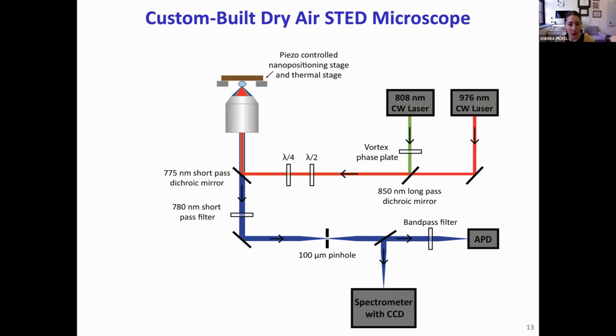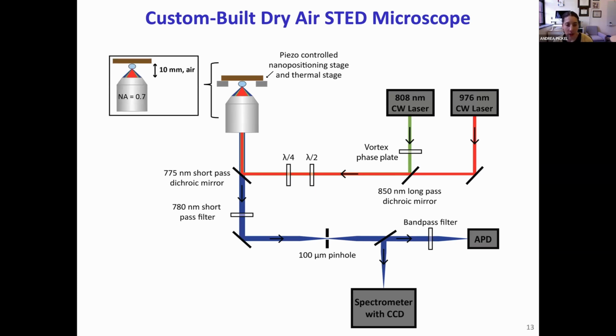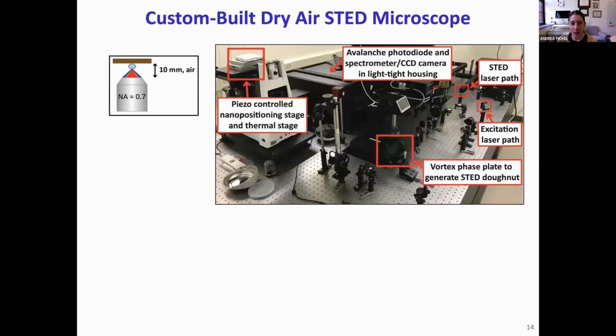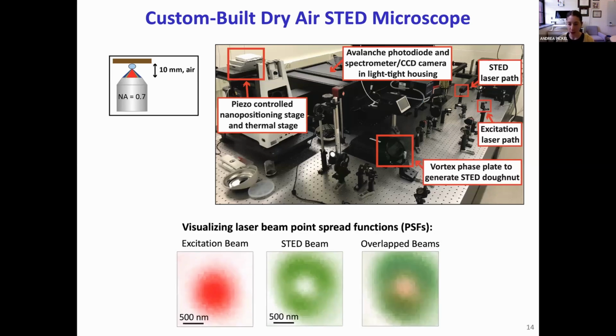We collect the emitted luminescence, which is primarily in the blue wavelength range, filter out any residual excitation or depletion light, and then we send that luminescence either to an avalanche photodiode or a spectrometer. We use a dry air objective lens that has a numerical aperture of 0.7, and it also has a working distance of 10 millimeters. And so that means we can probe our samples from very far away while simultaneously getting quite high spatial resolution, as I'll show in a moment. This is an image of the system we constructed in my lab at Rochester, and then images of the spatially overlapped excitation and depletion beams.